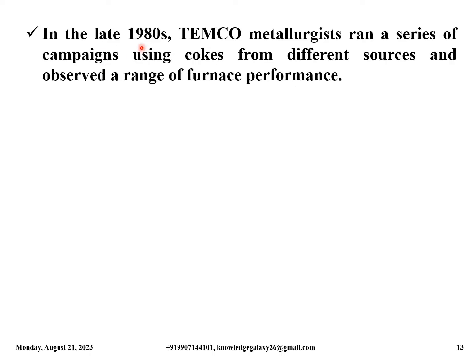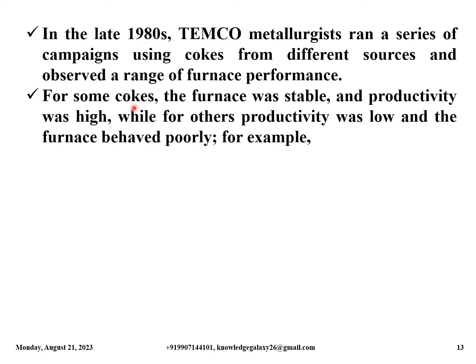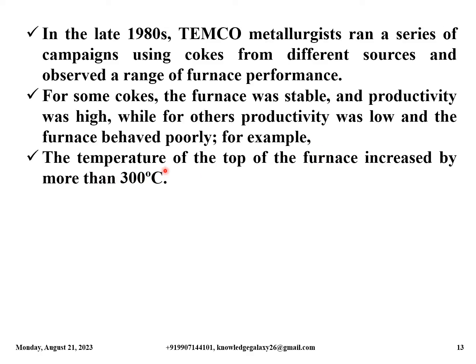In the late 1980s, TEMCO metallurgists ran a series of campaigns using cokes from different sources and observed a range of furnace performance. For some cokes, the furnace was stable and productivity was high, while for others, productivity was low and the furnace behaved poorly. For example, the temperature at the top of the furnace increased by more than 300 degrees Celsius.